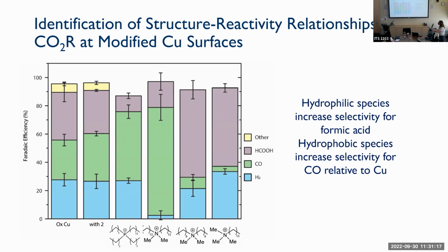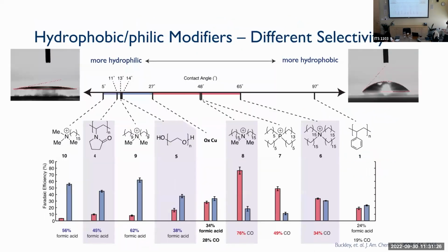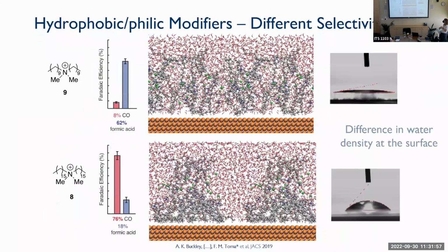And so we basically found a correlation between hydrophilicity and hydrophobicity and CO production. And you can see it summarized here. If you measure the contact angle of each functionalized surface that we made, and you compare it with the product distribution between formic acid and CO, you will find that a more hydrophilic surface will give you more formic acid, and more hydrophobic surfaces will give you more CO. What this is telling you is that, of course, water has a role in the reaction, and the amount of water specifically that is present on the catalytic site has a role in the reaction.